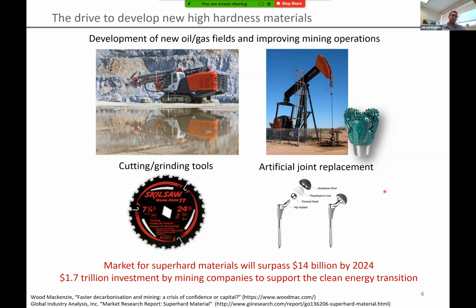There's a lot of applications for super hard materials that maybe a lot of people wouldn't even think about. Things like artificial joint replacements. If you have to have a joint replacement early in life, these artificial joints still need to be fairly wear resistant, because over time an artificial joint replacement is going to last on the order of maybe 5 to 15 years, depending on how much natural wear there is. And so if we can think about replacing specific parts like the femoral head in the artificial joint replacement with a wear-resistant, high-hardness material, these types of joints are going to last significantly longer. This is a pretty large market.